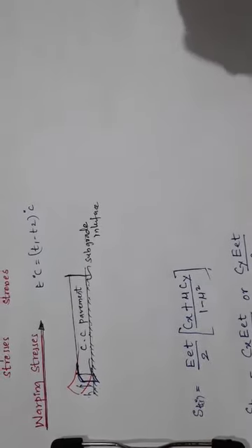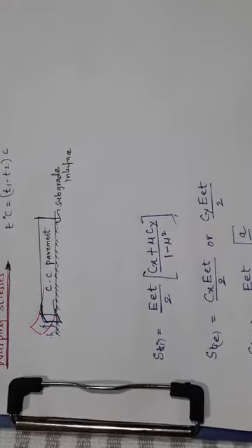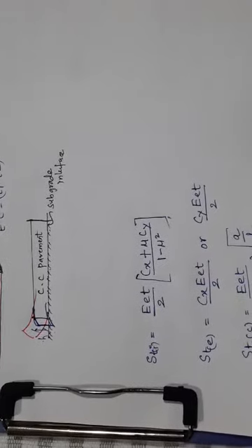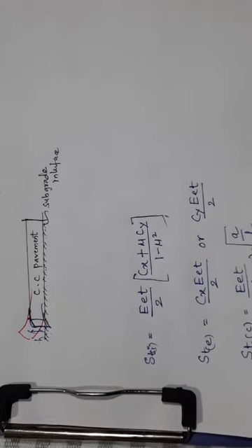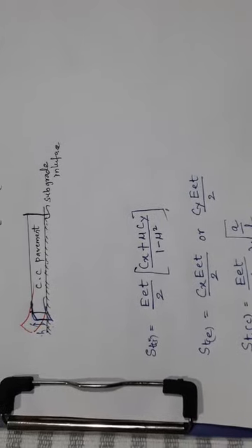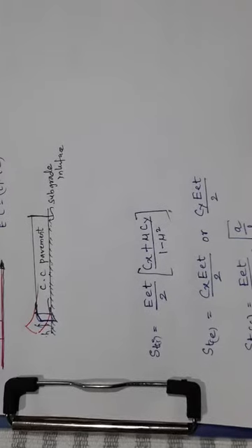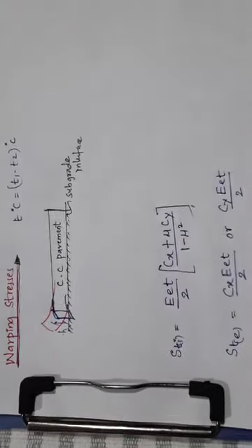So as I told, the temperature stresses developed in the cement concrete pavement are due to the variation of the slab temperature. The variation in temperature across the depth of the slab is caused by the daily variations, whereas an overall increase or decrease in the slab temperature is caused by seasonal variations. These are the warp stresses, the daily variations.